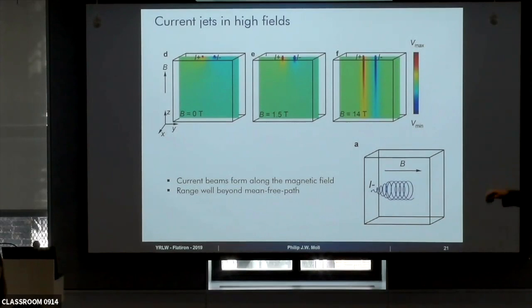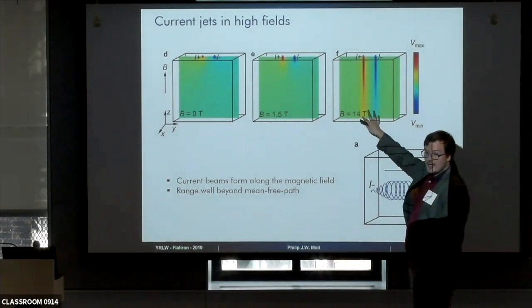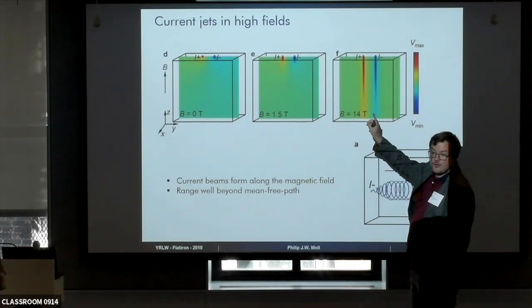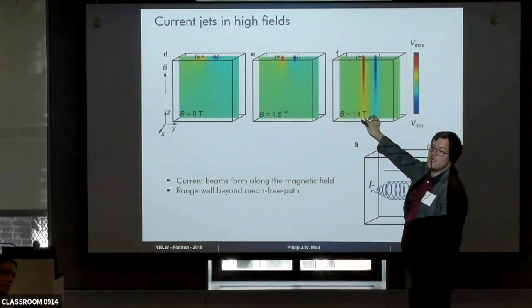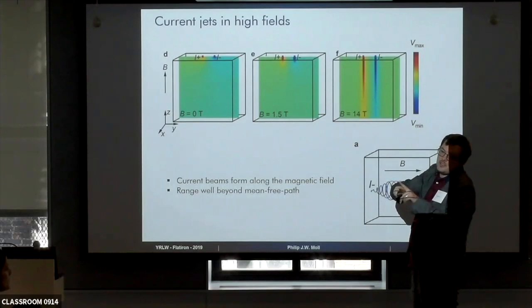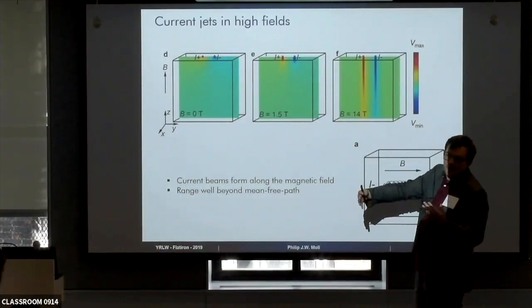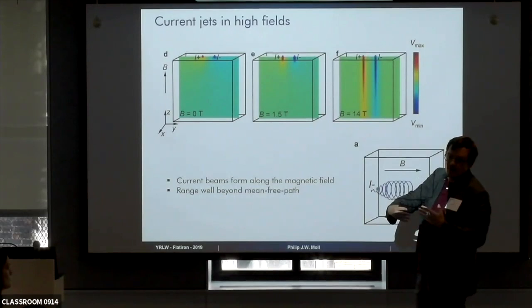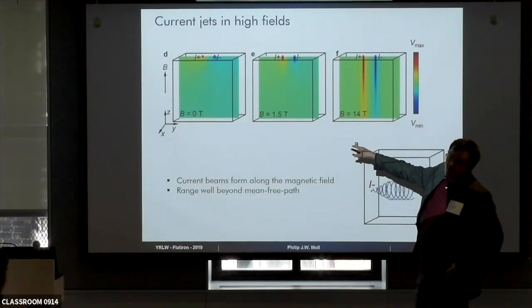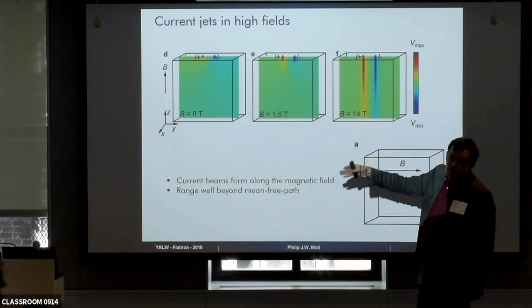The key thing is, of course, that this picture explains rather well what we see. So, okay, this will be the dominant effect. But on the other hand, what this will do is lead to very, very non-trivial electric field distributions, and in particular also E dot B distributions in this thing. So really what I think needs to be done is that we need to have some sort of self-consistent solution where you iterate a topological, chiral anomaly effect-induced conductivity, then redo the semi-classical version, and so on until this converges. And this might be interesting because maybe we could see beam deformations, maybe we could see differences from the semi-classics.